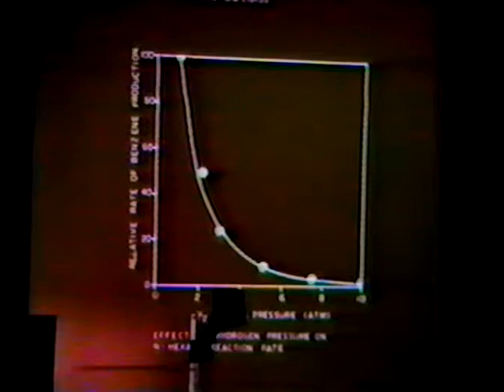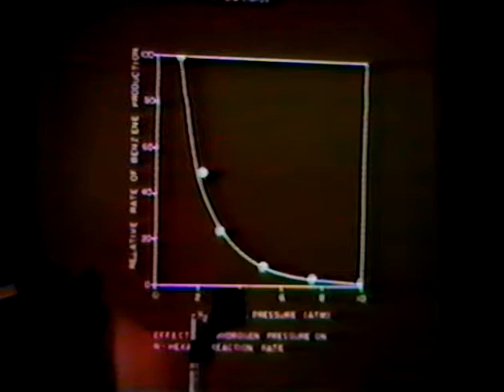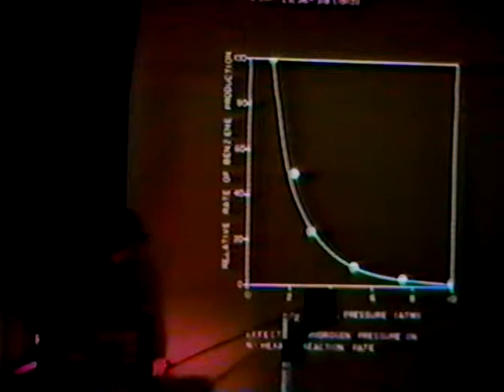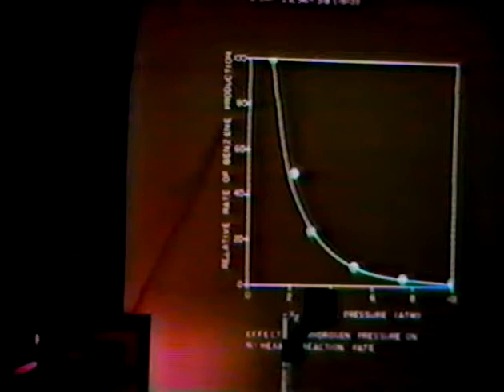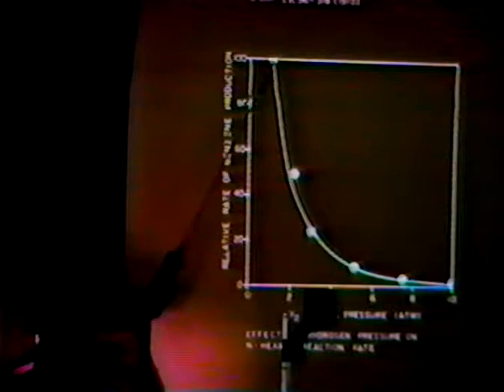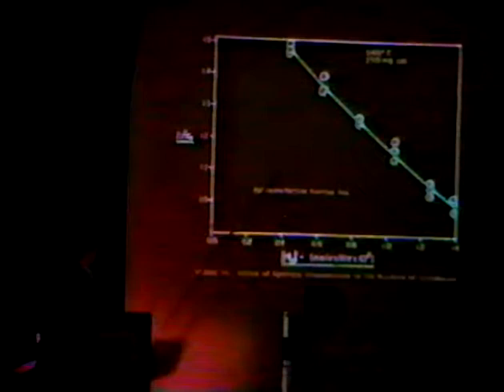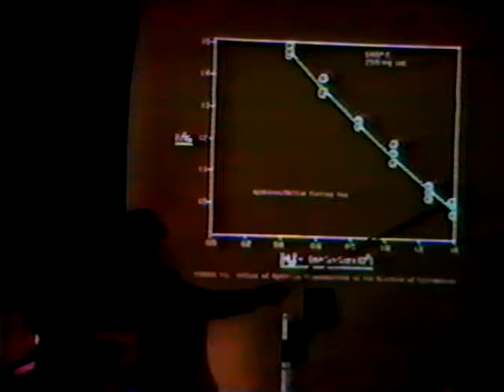If you do keep the hydrogen present, the catalyst is stable. We have to keep at least half an atmosphere or so of hydrogen present to keep this catalyst stable. But look what happens to the reaction rate with too much hydrogen. Here the partial pressure of hydrogen is going from one atmosphere up to about 10 atmospheres. Notice that the higher the hydrogen pressure, the lower the benzene production rate from normal hexane. So we're constrained by the fact that we can't even go lower than one atmosphere pressure, and as we drop the pressure the rate still continues to climb. This was at 540 degrees centigrade.